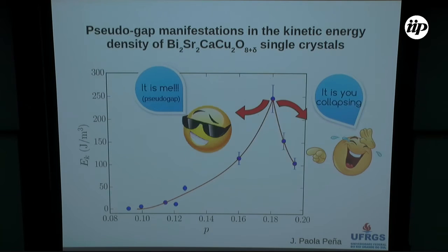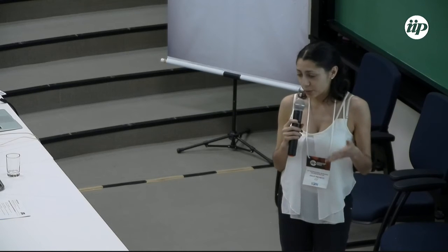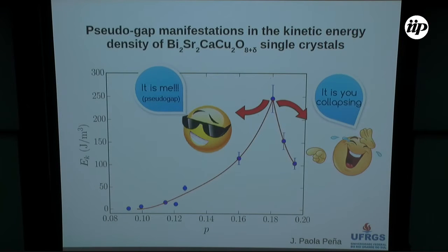Hello, my name is Paola. I am a postdoctoral fellow at Universidade Federal do Rio Grande do Sul in Porto Alegre. This work is about the kinetic energy density in several single crystals of this system, the bismuth 2212. We find that this kinetic energy density, which is a purely superconducting parameter, when plotted as a function of the hole concentration, shows this peak. And we observe the same behavior in the superfluid density, which we obtain from this type of measurements too. We think that this is a manifestation of the pseudogap phase inside the superconducting phase.